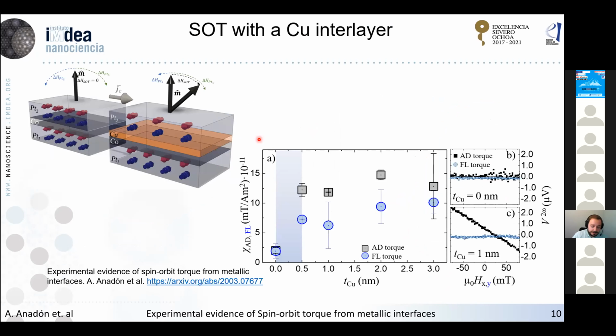So basically, if we take these samples and measure the second harmonic signal of the voltage, what we see is that when we introduce the copper interlayer, we observe almost a 10-fold increase in the anti-damping torque and a slightly smaller one in the field-like torque. If you see this problem without taking into account the interfacial effects, copper should be almost transparent to the spin currents, because copper has a very, very high spin diffusion length. So basically a spin current should go through copper as if there was nothing there. But what we are seeing is not that.